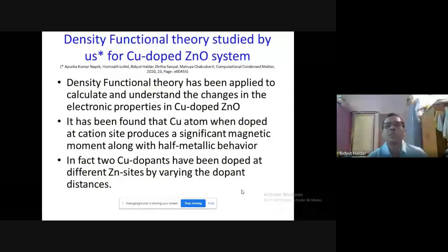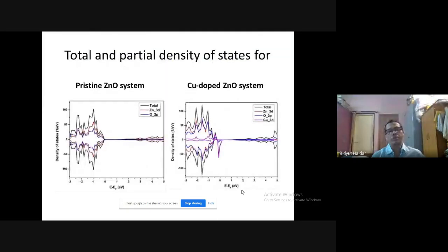In our earlier paper in Computational Condensed Matter, we have done some density functional theory studies on copper doped zinc oxide systems in order to understand the changes in the electronic property in copper doped zinc oxide. And it has been found that copper atoms, when doped at cation sites, produce a significant magnetic moment along with half metallic behavior. In fact, two copper dopants have been doped at different zinc sites by varying the dopant distance. This is all done using density functional theory. Before you, you have two figures. On the left, you have the pure zinc oxide system. You can see the density of states is symmetric, whereas on the right, you have the copper doped zinc oxide system, where you can see a bit of unsymmetric behavior.